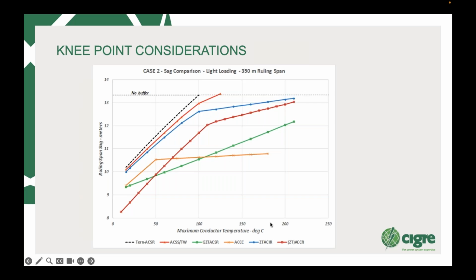Or you could do the ZTACIR invar core. Now you can see that there's your invar, invariable core. And it does not then sag very much more once it hits that knee point. The knee point is a point at which all the weight or the load goes onto the core. And you want that done as soon as you can. Lower is better, so that you can get a higher temperature before hitting your sag limit.